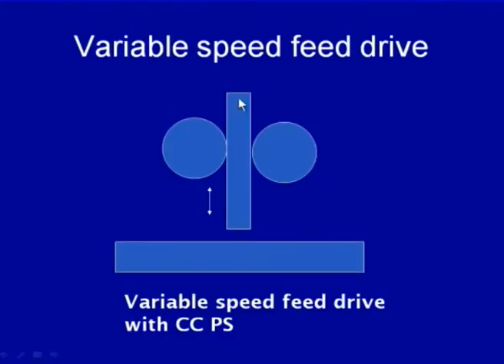So, for constancy of the arc gap, it is necessary that this gap is maintained by changing the feed rate of the electrode, and this change in feed rate of the electrode is obtained by changing the RPM of the roller feed drive system, and the change in roller feed drive system is obtained by changing the current being fed into the motors which are being used to rotate these feed drive system.